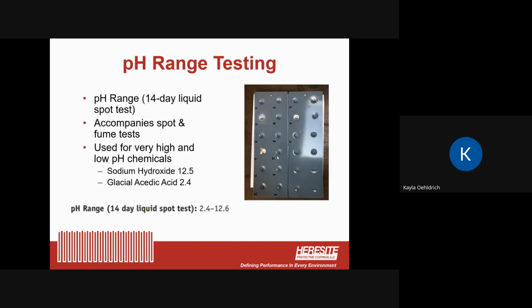So pH range, quite simply, is used in all of the previous tests. In both the spot and fume tests, we test the pH range to see where it's at. And then it helps us determine what type of testing we need to do. If it's on the high or low range, we may spend more time on it. So on the bottom there, that's just a quick view of what you see on our P413 technical data sheet. The most acidic, lowest pH that we test is 2.4, which is glacial acetic acid, and the highest is sodium hydroxide.